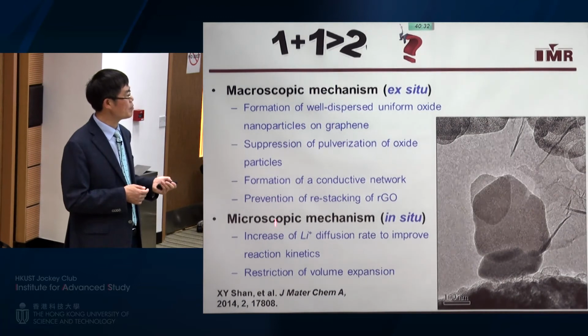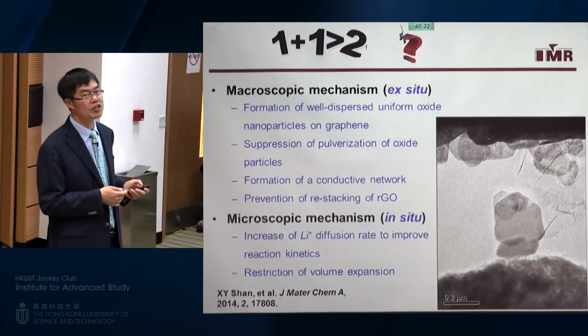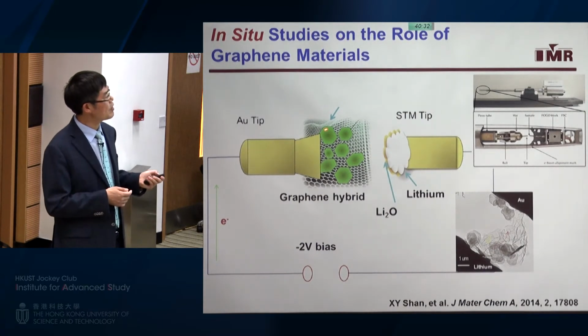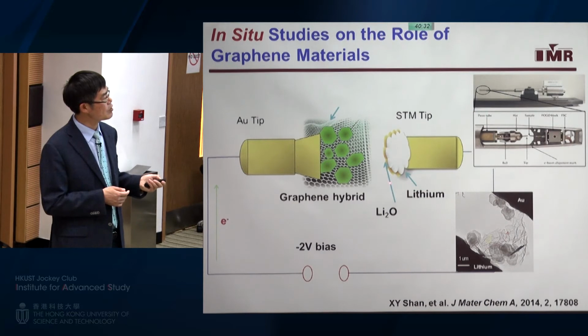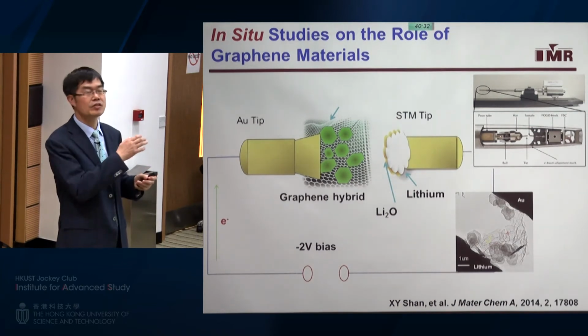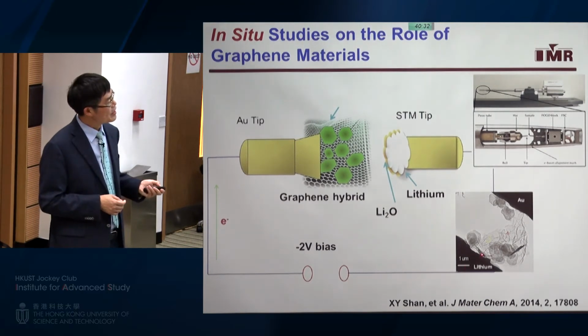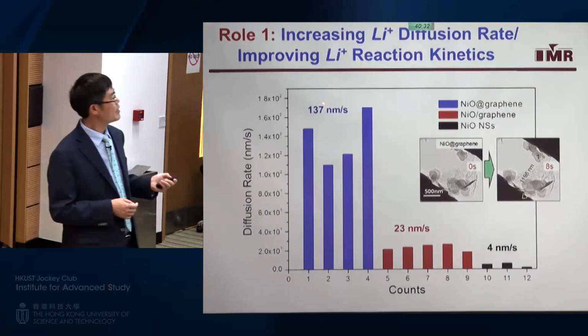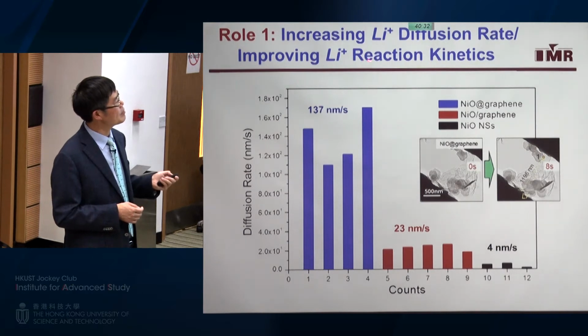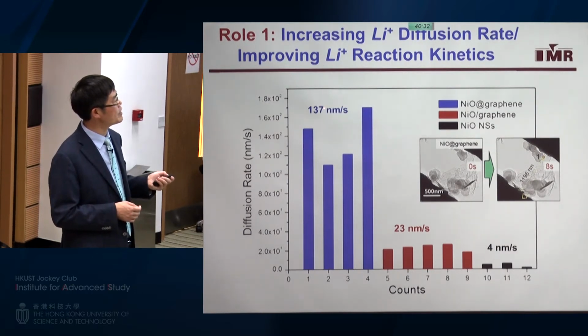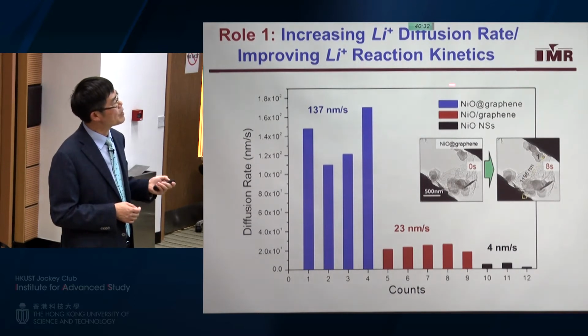And from the microscopic way, again, we use in situ investigation. So we have this graphene hybrid particle on this electrode, and then we have lithium on this electrode. Because lithium is ready to be oxidized to form lithium oxide, this lithium oxide can be used as the electrolyte in the in situ TEM. Then we can measure the diffusion of lithium from this part to this end. So then we calculate the lithium diffusion rate.